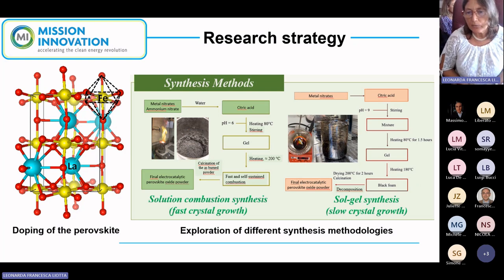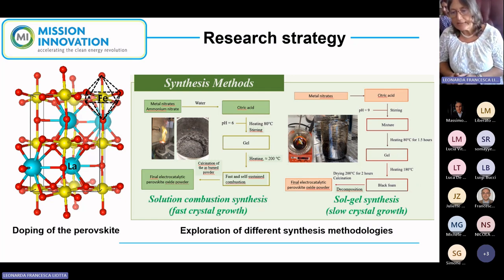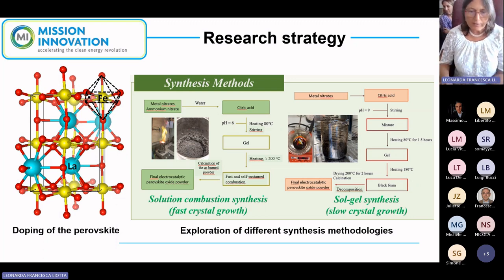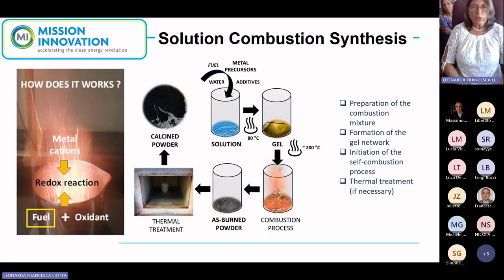Both the methodologies that we use are based on citric acid. One consists in a fast crystal growth, which is solution combustion synthesis, and another is a slower crystal growth and is a more typical sol-gel inorganic synthesis. I will describe this method in a few minutes. Solution combustion synthesis is essentially a redox reaction between fuels and oxidizers, so a fuel and an oxidant.